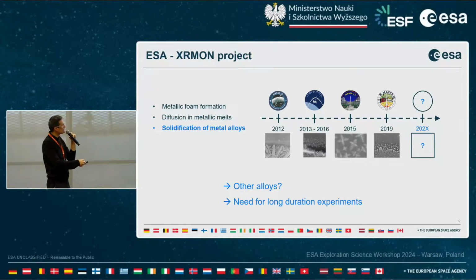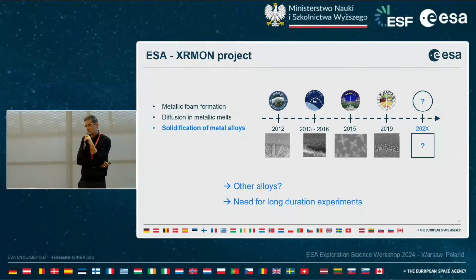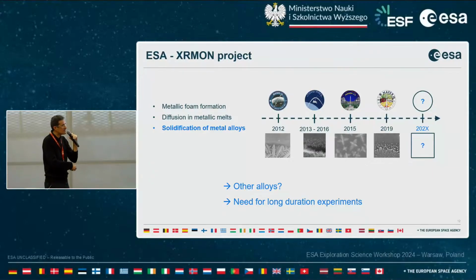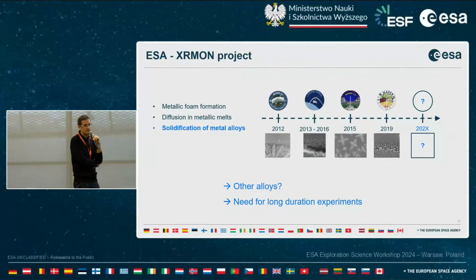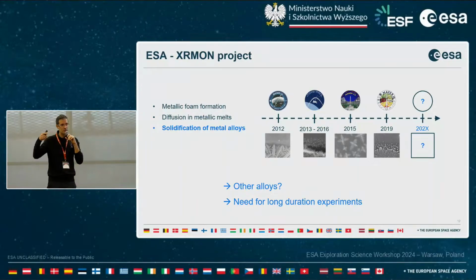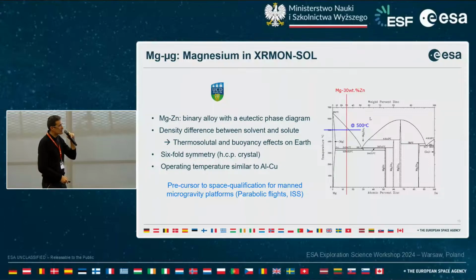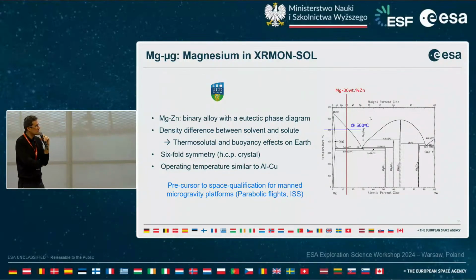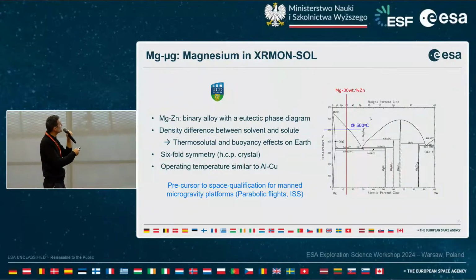And also a need for longer duration experiments, because typical solidification experiments can last half an hour, 1 hour, and sounding rockets only provide a few minutes of microgravity. So there is also a clear need for long duration experiments for solidification and also for diffusion experiments, as I mentioned before. So regarding the use of another base material, there is a work from the colleagues again at UCD in Dublin, which investigated the relevance of magnesium-zinc.